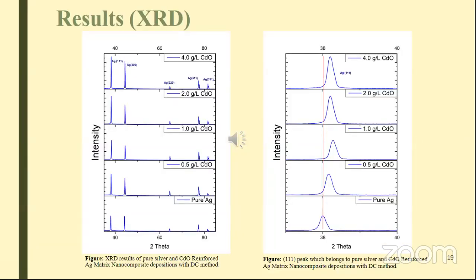As you can see from the XRD results, sharp reflections were observed and they correspond to the 111, 200, 220, 311 and 331 reflections of silver. XRD peaks do not show the corresponding reflections of cadmium oxide due to the small amount of reinforcement in the silver matrix. The highest peak is the 111 reflection in this result.